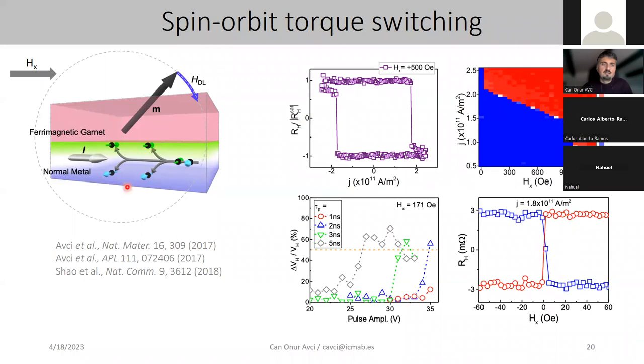Otherwise, the magnetization would just precess around the core, but cannot be deterministically switched. You can break that symmetry by using an in-plane field. And by doing this kind of measurement as a function of different in-plane fields, you can also see the switching diagram of the field. So where this transition between blue and red is basically the critical current for a given field value here.